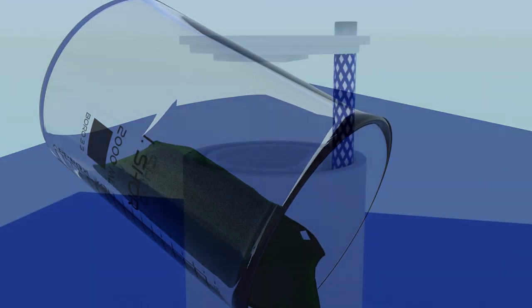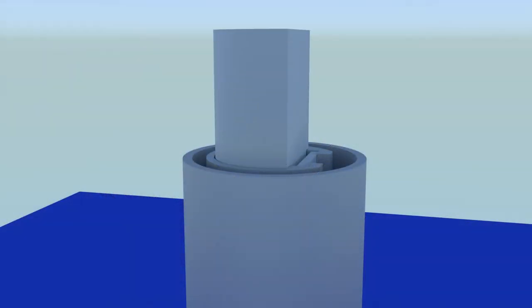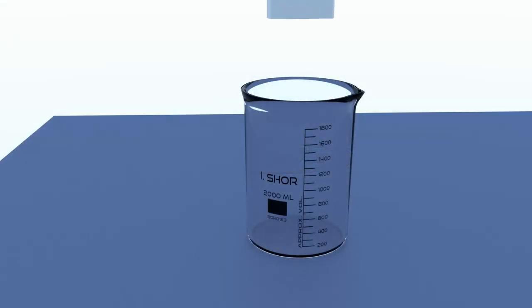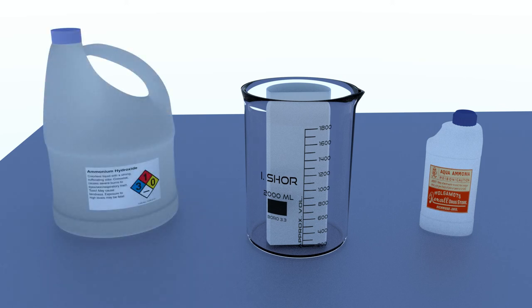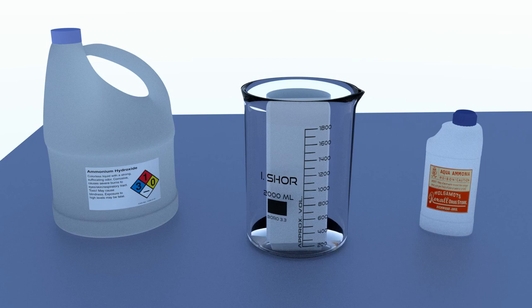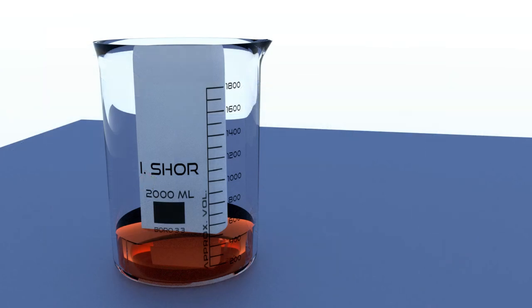Remove the pouch and place it in the empty beaker. For this part of the process, you will need aqua ammonia, also called ammonium hydroxide. This solution is similar to household ammonia but about 10 times stronger. Add enough ammonia to cover your platinum group salts. When all the PGMs have dissolved, remove the pouch.